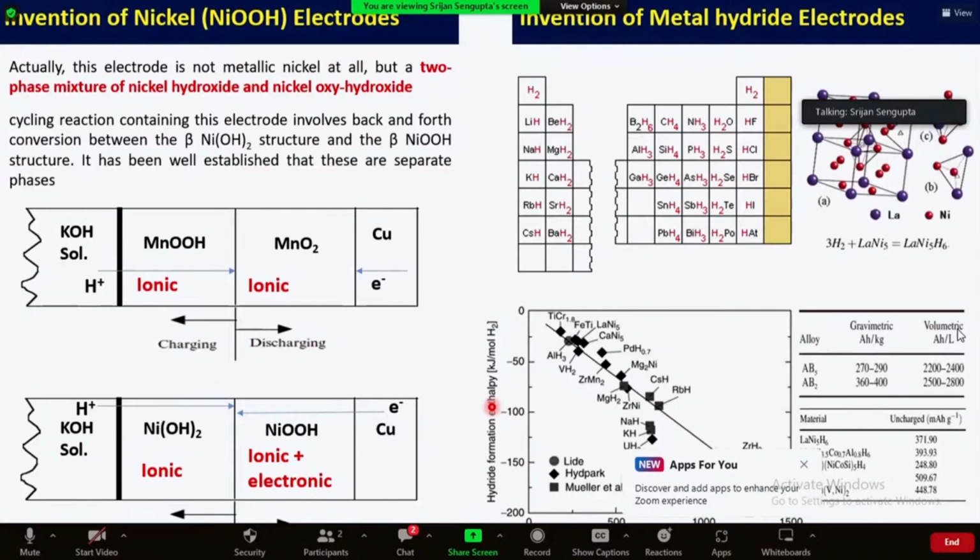So when you charge that battery, there is no problem for the electron migration at the surface where the charge transfer is going on. So you can have complete reversibility. And also, one point is there: here nickel is converting from 3 plus to 2 plus. So it's not 2 plus to 4 plus. So your ionic radius also does not change. Your volume expansion can be controlled and the battery does not degrade mechanically.